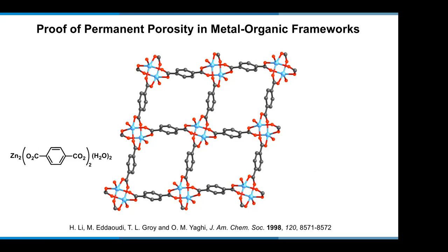The development here and the important thing that we contributed at the time was the fact that you could use clusters like these, aggregates of metals, as building units to make MOFs. Intuitively, these clusters are rigid, and therefore we thought and later showed that in fact they make architecturally robust frameworks that, when you evacuate the pores, don't collapse. So these we call secondary building units or SBUs.